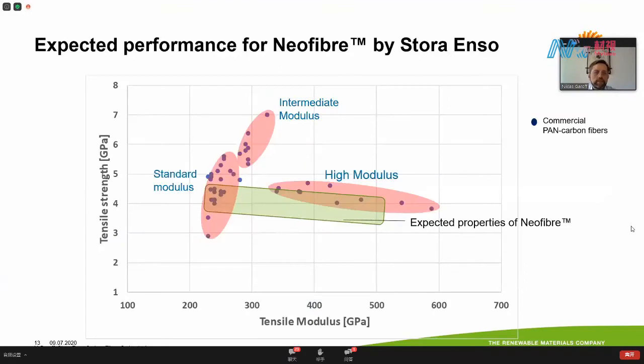Now, this slide shows the tensile strength and tensile modulus of commercial carbon fibers. Carbon fibers can be grouped into 3 different families, depending on what performance they deliver. The biggest group is standard modulus carbon fiber, which have a modulus between 230 and 270 gigapascal, and a tensile strength of between 3 to about 5.5 gigapascal.